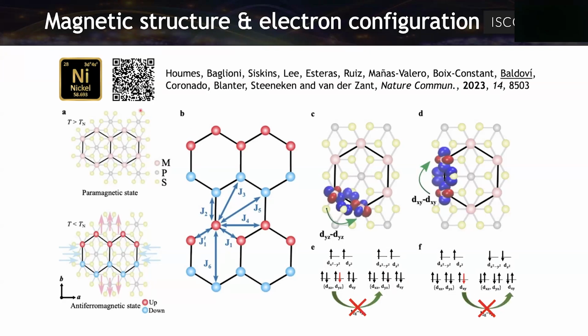If we go now to nickel, in the case of nickel, all these states, the t2g, are fully occupied. It's d8, and in this case, this is cancelled and this is cancelled, so the material cannot provide this kind of enhancement of these properties, because the mechanisms don't take any place. They cannot hold the electrons because everything is full here.